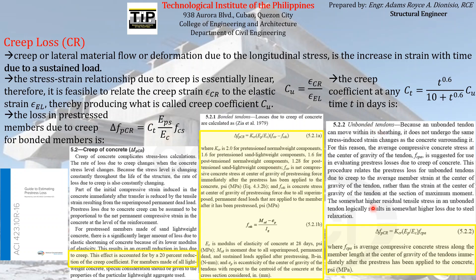For the case of unbonded tendons, you can use this formula. We just replace the stress here with FCPA, which is the average compressive concrete stress along the member length at the center of gravity of the tendons immediately after the pre-stress has been applied to the concrete — in other words, the stress at transfer averaged along the member length at the center of gravity of the tendons. These formulas are similar to the formula we have here, although they came from the ACI-ASCE Joint Committee.